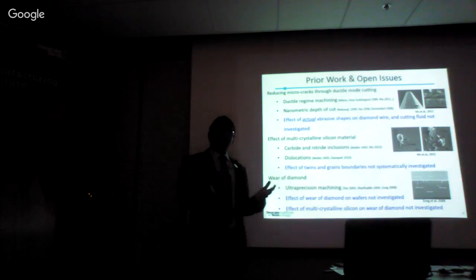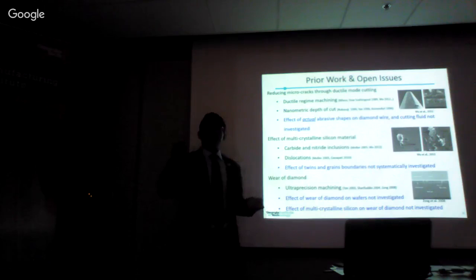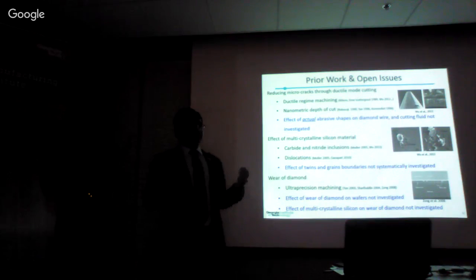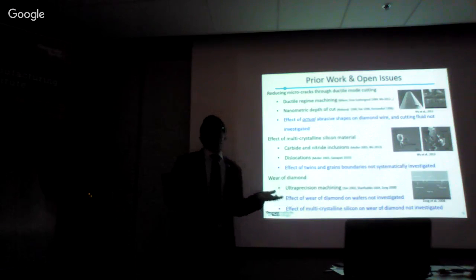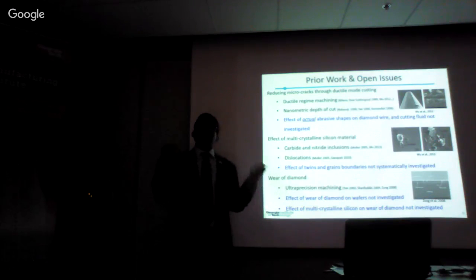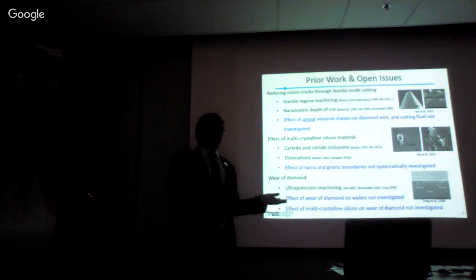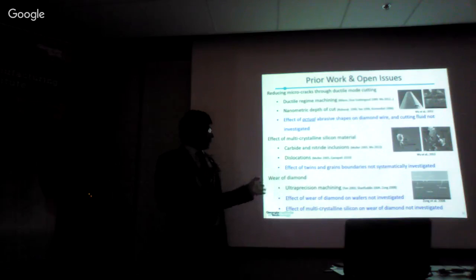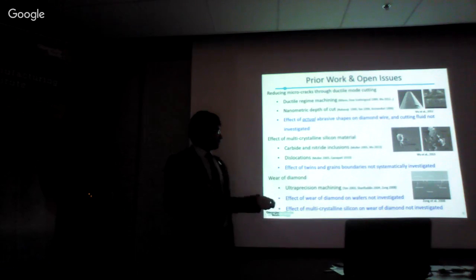Secondly, about the wear of diamond, we found from our industrial collaborators that one of the major challenges in cutting multi-crystalline silicon is greater consumption of the expensive fixed abrasive diamond wire compared to cutting monocrystalline silicon. And there has been no work in prior literature about the reasons why the wear of diamond is more when cutting multi-crystalline silicon compared to monocrystalline silicon. So that forms one of my major tasks in the thesis.